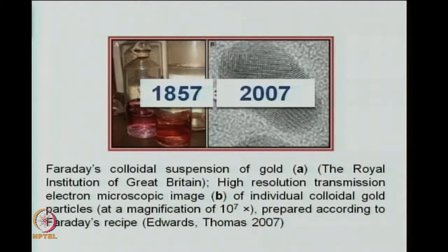on the right hand side, which shows you clearly the pattern which one should observe for a gold particle, and you can be sure from the spacings between these lines that you observe that corresponds to gold, and this is a transmission electron microscope picture of gold nanoparticles, from which you can see the size of the particle, and also you can prove that it is a gold particle by measuring the distances between the atoms or the lines which are formed by the atoms in real space.